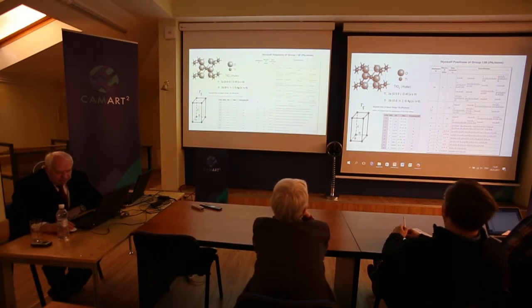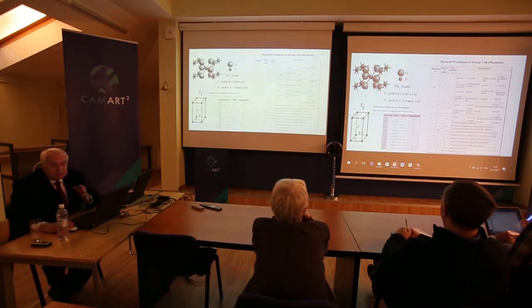If it is clear, then I can say that plane M, which is orthogonal to the fourth order axis, is a horizontal plane. In this plane lie, of course, this titanium and these 2 oxygens. And this is a simple reflection plane, because when you reflect in this plane, this diagonal comes to the equivalent. So this is the M plane, a mirror plane.